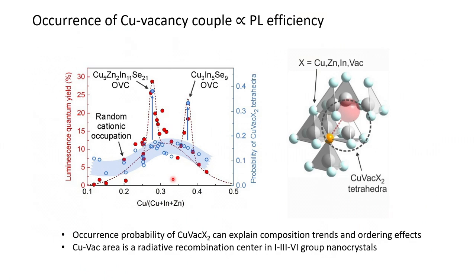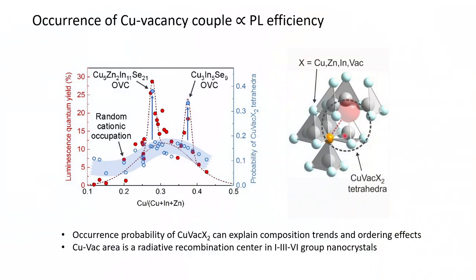So in a nutshell, we explained that the occurrence probability of copper vacancy couples is proportional to the luminescence, so it can explain both composition and ordering trends. And this is what you see. This is the structure, with copper in orange and the vacancy in semi-shaded red. So with that, we answer where the light is coming from. The copper and vacancy couple is the workhorse for this material. So the more you have of this, the more efficient your light is.